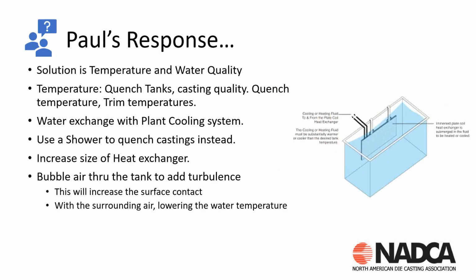So let's talk about quench tanks. With the quench tank, you've got a couple items: temperature and water quality. So let's divide these into a couple pieces. First off, with the temperature, we're concerned about the casting quality, the quench temperature, and the trim temperatures. If the casting is extremely hot coming out of the quench tank, that's going to affect trim shear, the trimming operation. So we want that temperature to be uniform or a lower temperature.